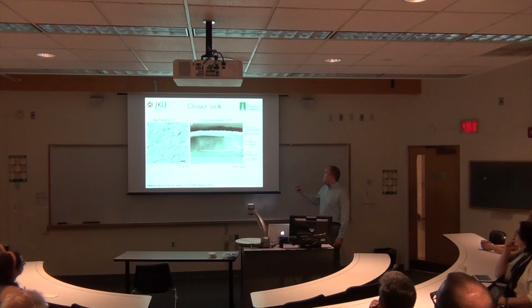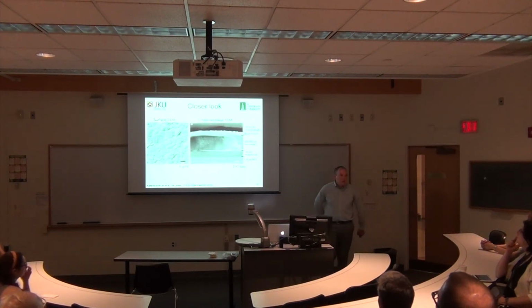It could, but look at the thickness here. It's 200, 300 nanometers, compared to the grain size, which is several microns. So it's not inconceivable, but primarily I think you're looking at single grains.